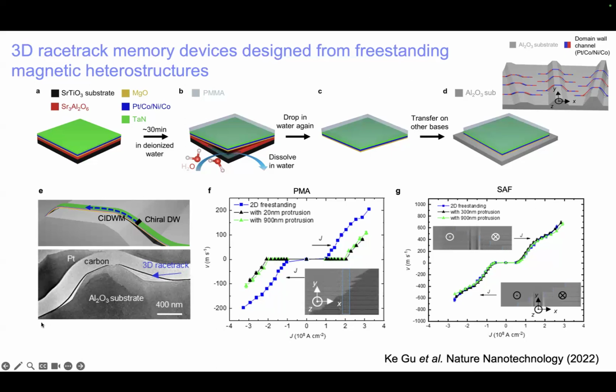You can see in this cross-section transmission electron microscope image that the 3D racetrack is the black line. It's almost following the hillock in the sapphire substrate. So it seems to work. And then what we found was that the domain walls can be moved through this essentially 3D racetrack. So it's the first attempt to create a truly three-dimensional racetrack.